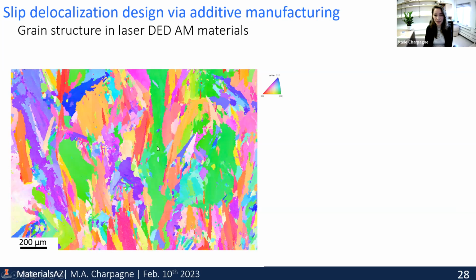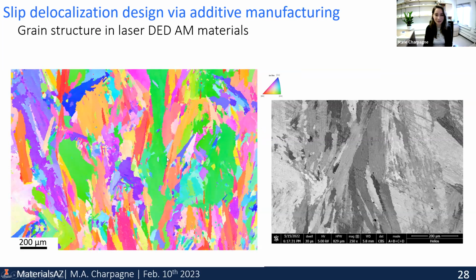It now just comes down to minimizing the number of defects and the defect density in those materials so that we can engineer their microstructure better. And this is a huge challenge because as we zoom in and look at what's inside those grains, we see very small regions, a lot of low angle grain boundaries, a lot of segregations, a lot of smaller particles, tiny keyholing. So there is a lot more to it, more than characterizing the grain size. And we think that EBSD alone, by characterizing the grain orientation and its distribution, will not help us too much. So we're looking into optimizing the substructure in those grains.